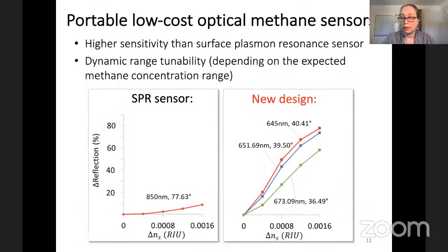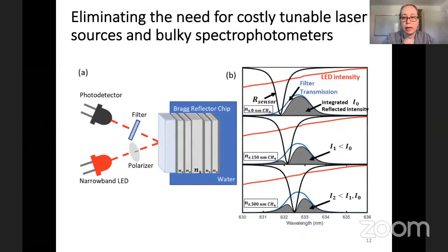Indeed, our sensor design operates at a single wavelength that you engineer by sensor design and composition, and it provides much larger sensitivity. You can see very, very small changes in the refractive index, and this range of changes corresponds to the actual changes of dissolved methane that is expected in the ocean environment. Despite the changes being so tiny, we can have a reflectance difference from almost 0 to 80 percent, which is very easy to detect with simple sensors. This is a practical implementation of a sensor. We would just be looking at the intensity changes under excitation by a simple off-the-shelf photodiode and LED. This is easily detectable in a wide range of changes of the refractive index that are typical for methane concentrations.